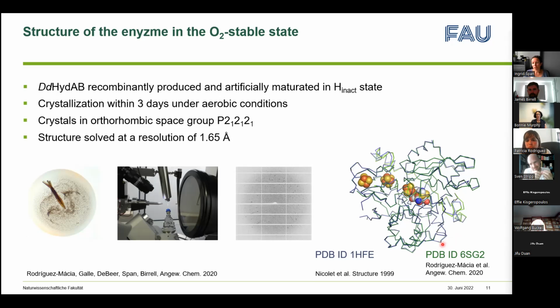When we solved the structure, the first thing we did was compare our overall structure to the previously solved structure, and we see that the overall architecture is very, very similar. We also see the cofactors, the H cluster, the active site and the 2 FeS clusters, and we see that they are fully intact. One thing that I have to mention is that in the active site, the 2-iron subsite that was maturated artificially is only 60% occupied in the structure.